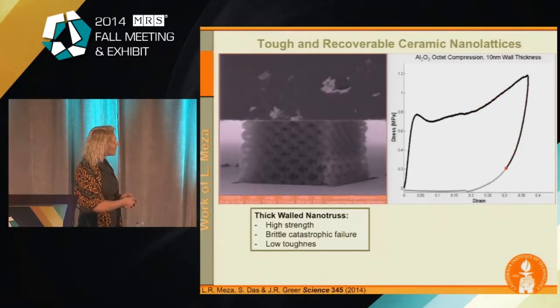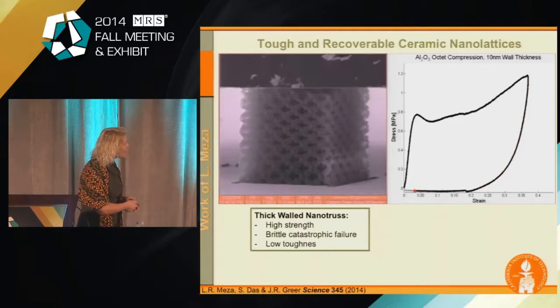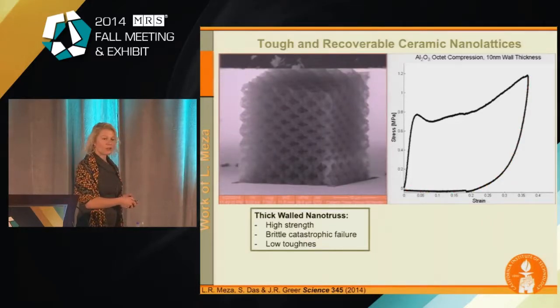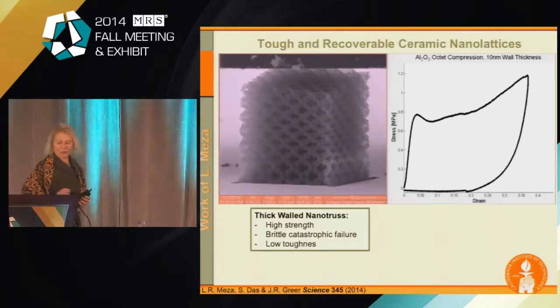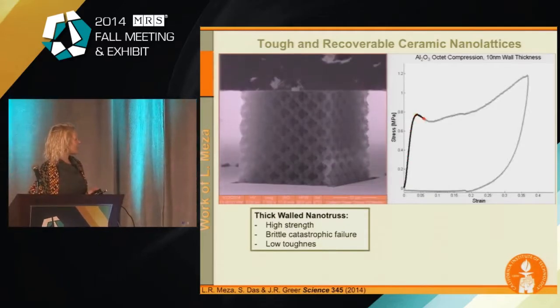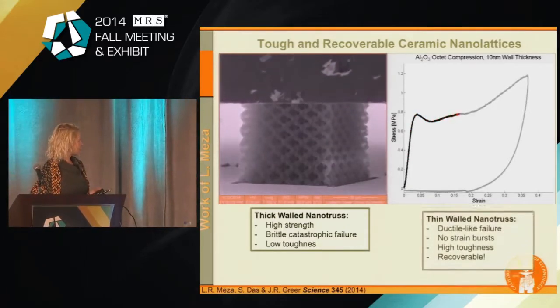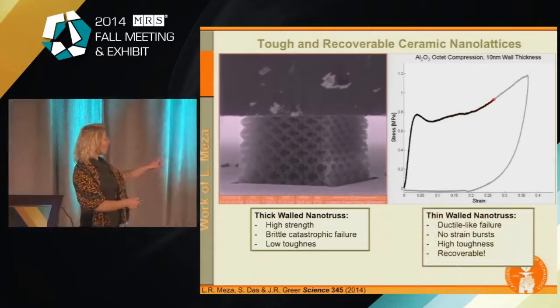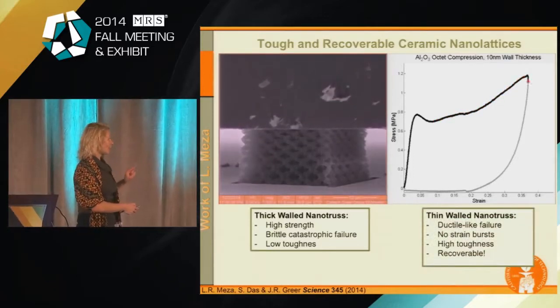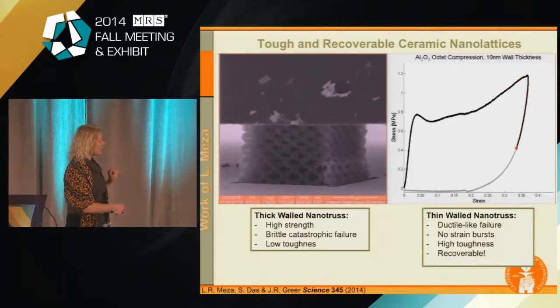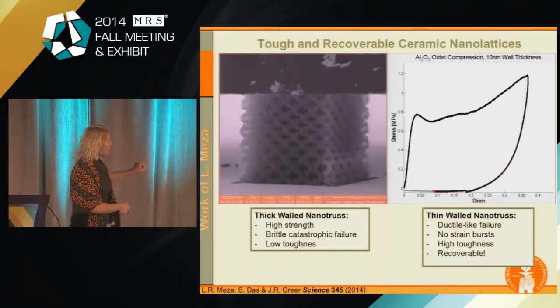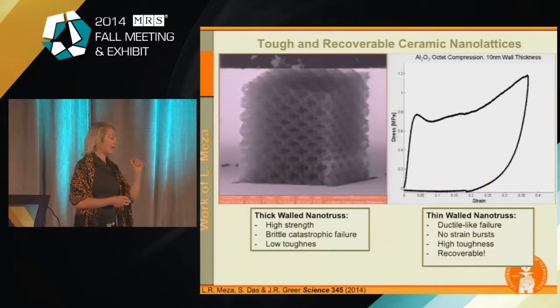So not only is it compressing almost to about 50%, but it fully recovers. So Lucas just made a ceramic that's 99% air that recovers after compressing it. These are not properties that you would expect, and these are very much not something that we would expect. And the only difference between these two is the wall thickness. So one thing that's very interesting to notice here is that the same material deposited by exactly the same technique wrapped around a three-dimensional architecture is able to exhibit completely different behavior.